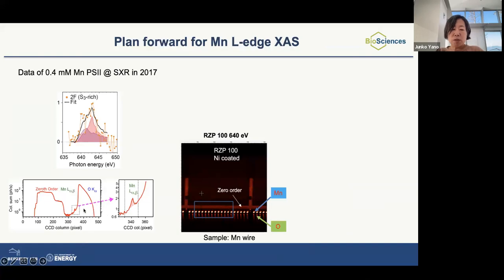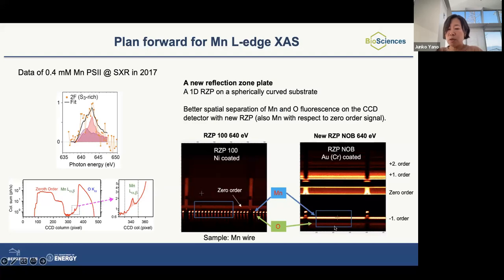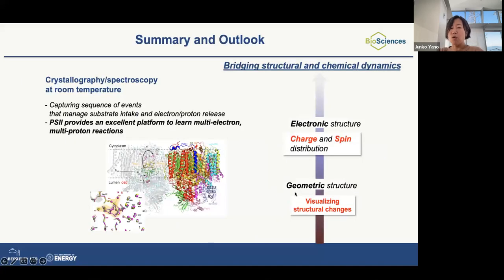Still, the issue we have is that in this setup, the manganese L alpha signal is sitting at the shoulder of oxygen K alpha. So the separation of manganese and oxygen signal is not quite enough in the current setup. In the new zone plate, we have a better separation of manganese and oxygen signals. So we think that using this setup, we should be able to get better data of manganese L-edge. So that's an ongoing study.